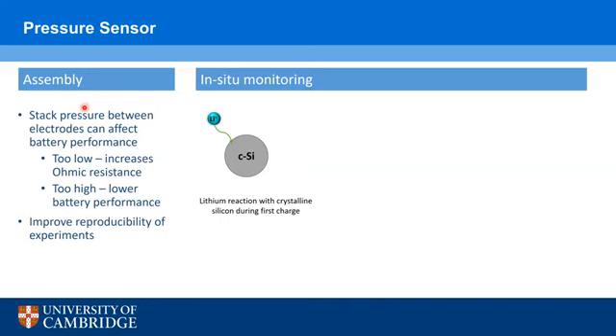This is because stack pressure is quite important when assembling these cells. If the stack pressure between the anode and cathode is too low, then we can increase ohmic resistances, and if it's too high, then it may lower the battery performance. And the other thing we propose to do is some in situ monitoring.